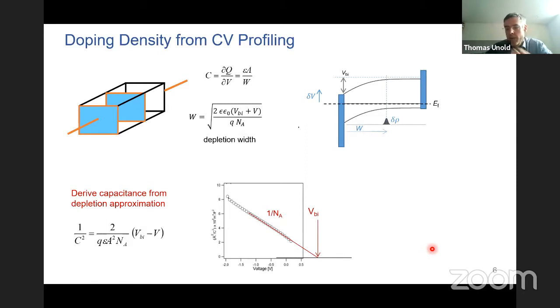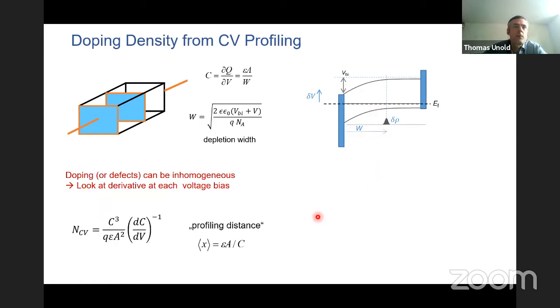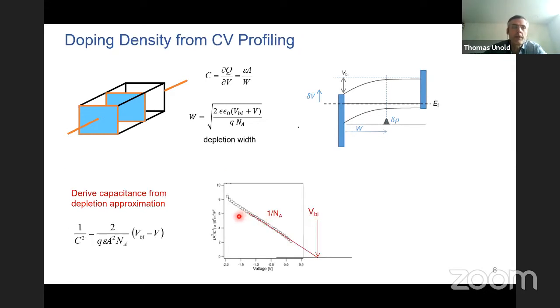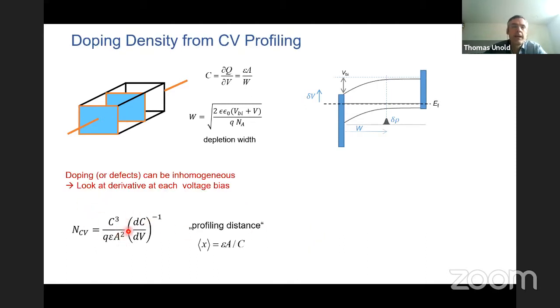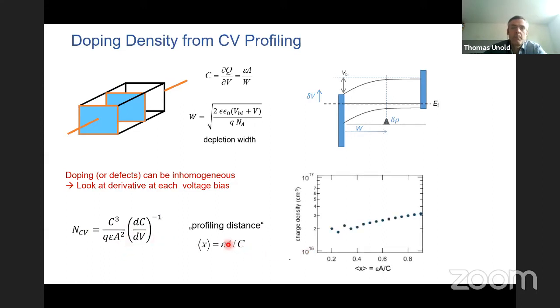It only works for the most ideal cases actually. So often it assumes that the doping is constant here in the device. So often it will not be, it will vary with spatial location. What you can do is then you take the derivative at each point. So I go back to each point of this capacitance versus voltage, you take the derivative, and you can again compute a relatively simple formula here. And then you can plot this at each point, and each point means basically one over the capacitance, because that is the depletion region. So at each voltage, this point here moves.